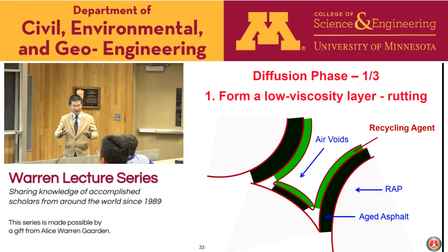In the beginning, the rejuvenating or recycling agent forms a low viscosity layer, like here, coating all the RAP material that's still coated by the aged asphalt. At this stage, asphalt mixtures with high RAP content might be subject to rutting, because the recycling agent acts like a lubricant. So that's what will happen.